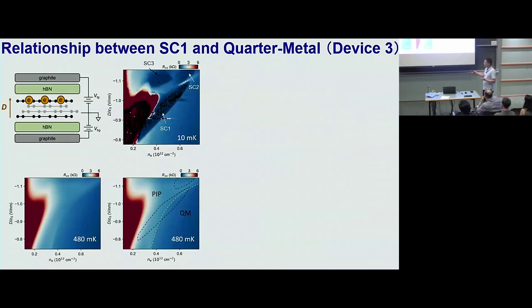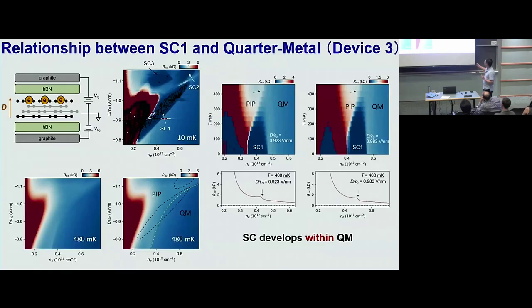That's true, but that's not complete, because when you cool down the sample even more, this boundary between the quarter-metal and this PIP metal state actually will shift to lower charge density. So at 480 millikelvin, it intercepts only this part of the SC1, but when you cool down even more, this boundary shifts to lower density, and the superconducting state emerges to the right of this boundary. And that tells you that the superconducting state really develops within that spin and valley polarized quarter-metal. Okay? So this boundary can be seen clearly as a kink in the line cut of RXX.